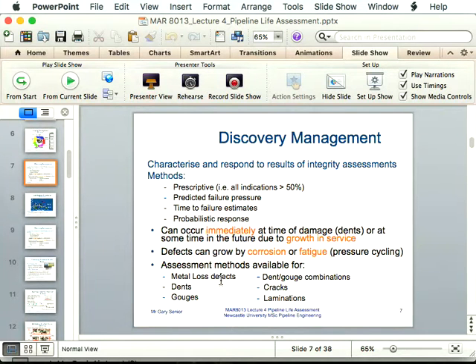So that's one thing that a dent does. And also, whoever dented the pipeline, they did work hardening on the surface, so they created a hard layer and potentially more cracking, because hard materials are more susceptible to cracking. So there's two things: it causes a hard layer, potential crack, and a stress concentration. Gouges are similar to metal loss defects in that it's a reduction in the pipe wall, but again gouges have this hard layer produced due to the impact of the indenter as well, so it's more complex to assess. And then dent gouge combinations, I'll come to right at the end.